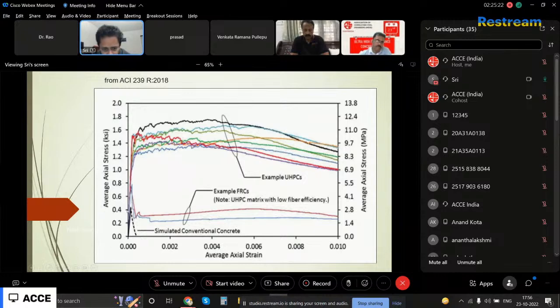So your conventional concrete is giving you somewhere around 2.8 megapascal, which is about 3 Newton per millimeter square of tensile strength at failure, tensile stress. 3 Newton per millimeter square for conventional concrete. For UHPC, we are seeing close to 8, on average 6 to 9. So say 8 here, 8 or 7. 7 Newton per millimeter square is what we are seeing.